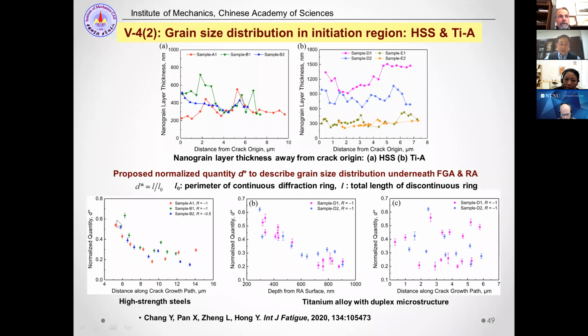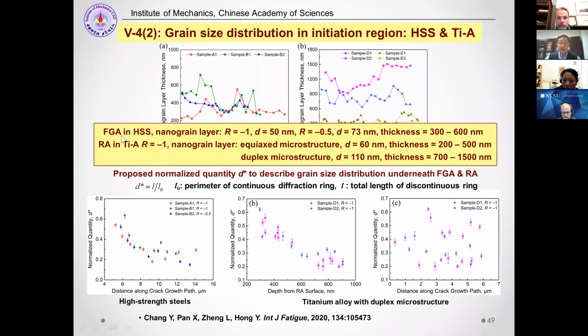By this quantity, we can describe the evolution of refined grains for high-strength steel and for titanium alloys. We can say that for high-strength steels, the grain size is 50 nanometers for -1 stress ratio and about 73 for -0.5 stress ratio, and thickness is between 300 and 600 nanometers. For titanium alloys with equiaxed microstructure, the grain size is about 60 nanometers, and thickness is about 200 to 500 nanometers. For duplex microstructure, the grain size is 110 nanometers, and thickness 700 to 1500 nanometers.